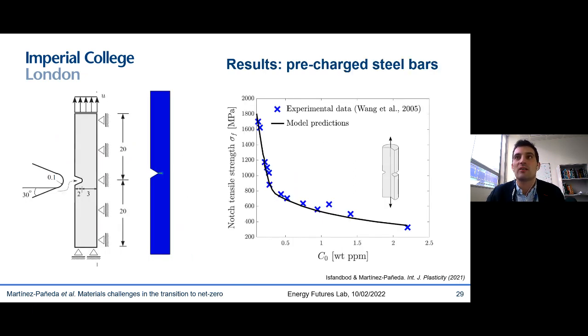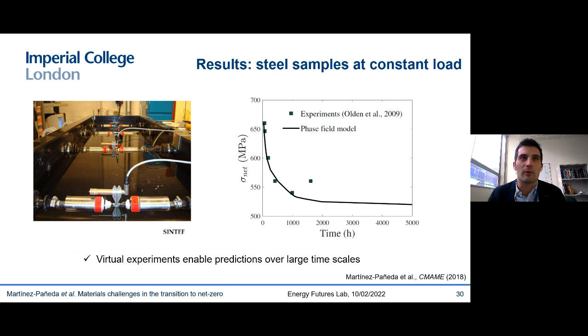And let me show also some quantitative comparison with experiments. You can see here, these are tensile bars of pre-charged steel bars. I can't remember what steel this was, but this is the notch tensile strength versus the hydrogen content. And you can see, of course, that it goes down, and the model agrees very well with experimental observations.